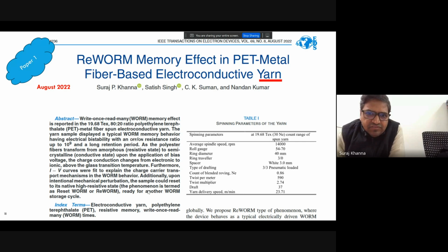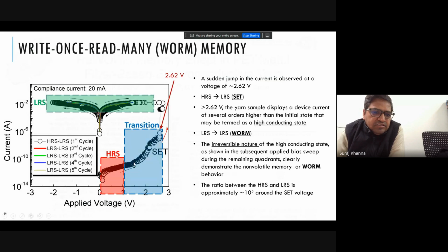In the first paper, since this is a semi-log plot, this is the current on the logarithmic axis, and this is the applied voltage. As you can see, initially it is in a high resistive state, with current in the femtoampere range. When it clears some threshold voltage, it starts accumulating heat, and due to Joule heating, it makes a sudden jump to the conductive state. Since this is a logarithmic scale, we are looking at a butterfly.